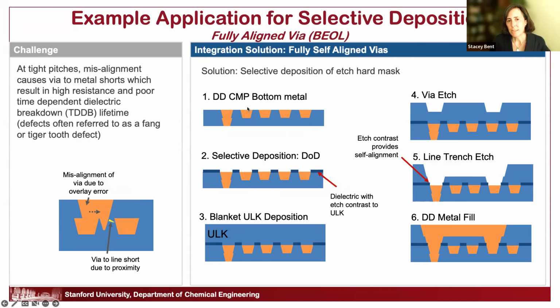So on the right is a process where one selective deposition step is incorporated into that to try to reduce this issue. So you have your bottom metal, and before you put down your next layer of this ULK, ultra low K dielectric, first, we're going to insert a step here where we do selective deposition of dielectric on dielectric. That's this DOD, where that dielectric you put down has some etch contrast relative to the ultra low K. So then you continue on the process here.